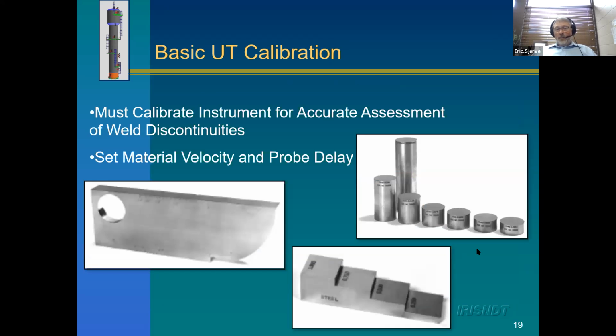So there's a couple of ways this is calibrated. The first part of the calibration is we need to know the velocity of sound in the material, because we can't position defects properly unless we know the velocity. So these are the calibration blocks that we use to set the velocity, and then we can calibrate that probe so we get the proper depths when we do an inspection.